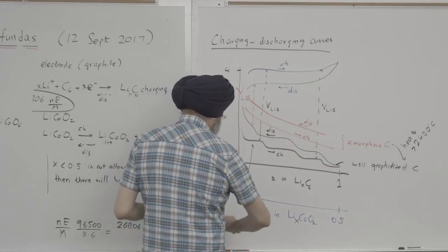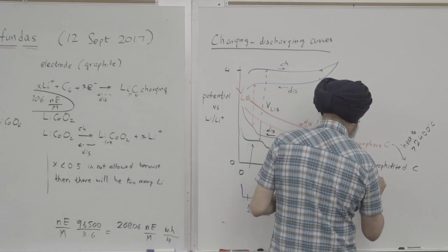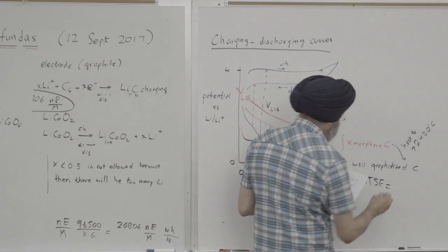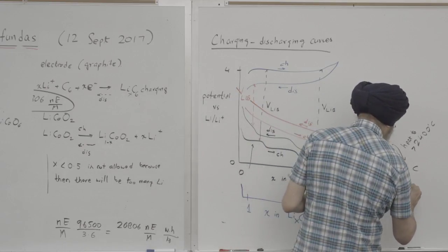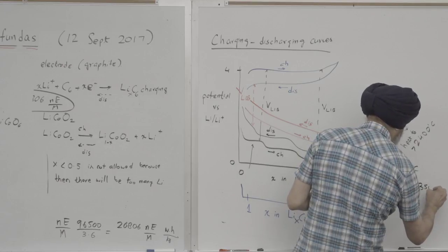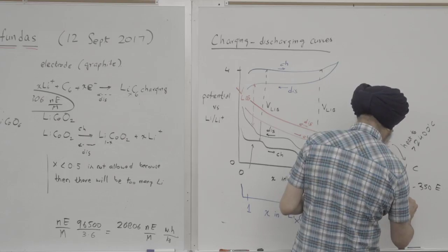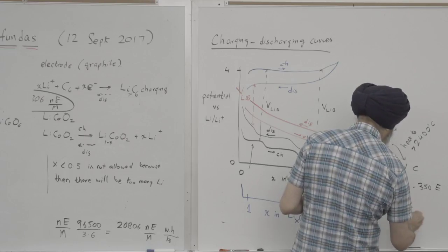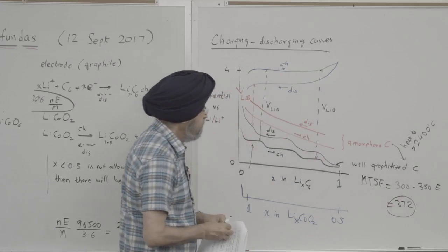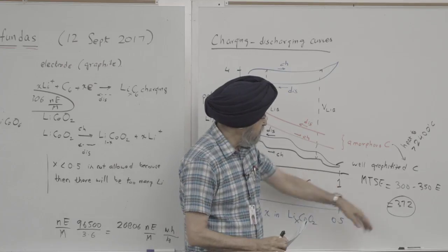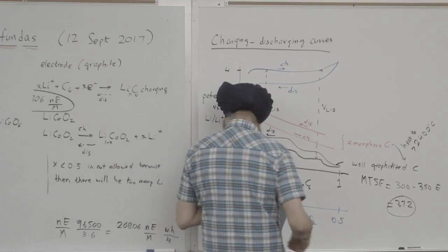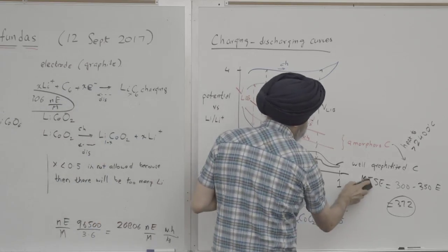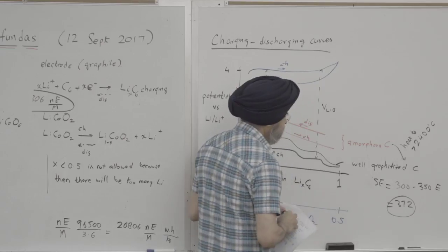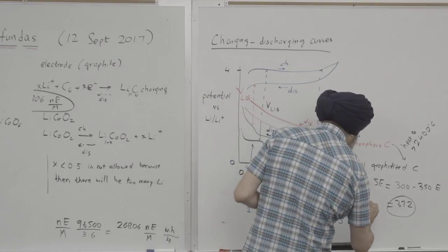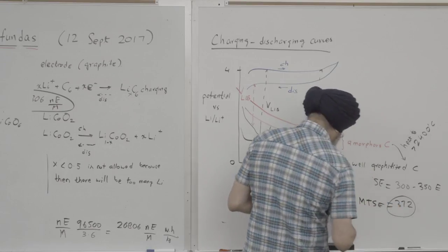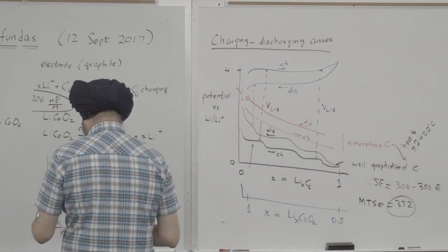So what is the practical specific energy of well graphitized carbon? It's about 300 to 350, and compare that with 372 that we calculated. It's pretty good. So graphite can get pretty close to its theoretical value. Okay, this I should just say specific energy. This is not maximum. So specific energy for graphite practically would be in this range, whereas the maximum theoretical specific energy is 372 that we calculated before.